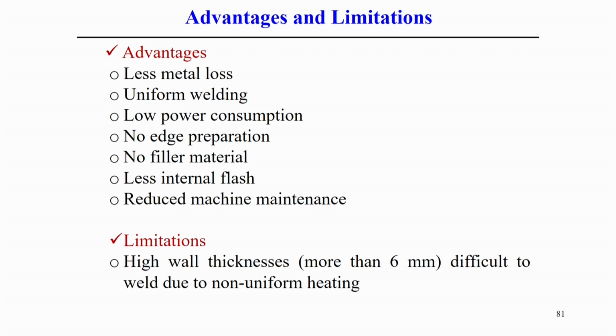If you look into the typical advantages and limitations of this process, the advantage is that there is very little loss of metal, and uniform welding. That is the basic feature when you try to join the welding of a pipe, and this process is very advantageous compared to other conventional welding processes, because the rotation of the arc throughout the whole structure creates uniform heat throughout the whole circular path of the pipe. So, that is another advantage. That is called uniform welding.